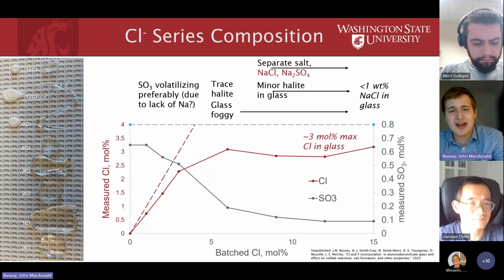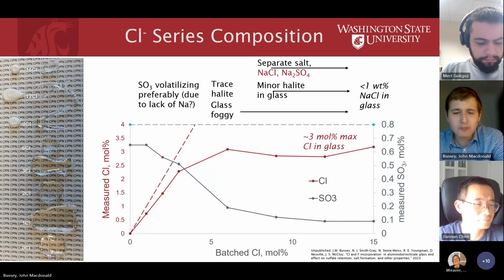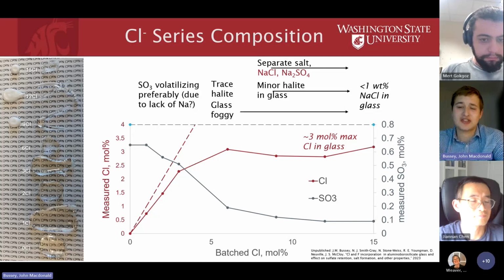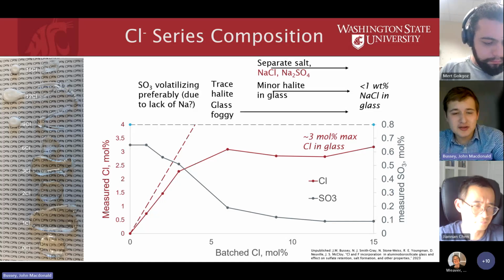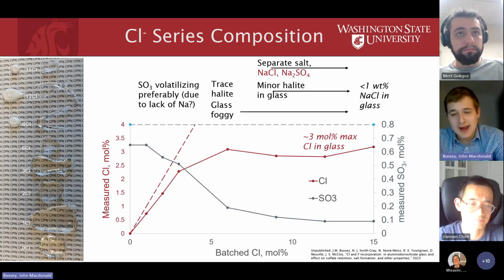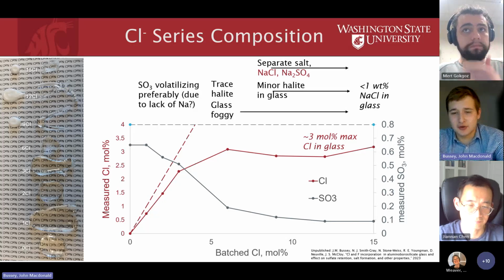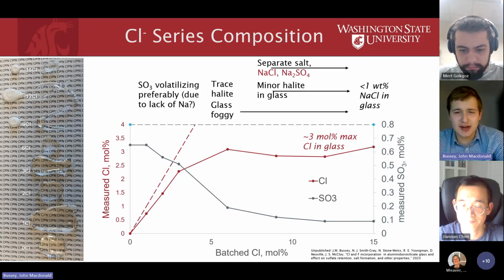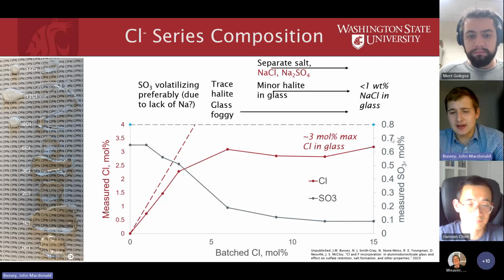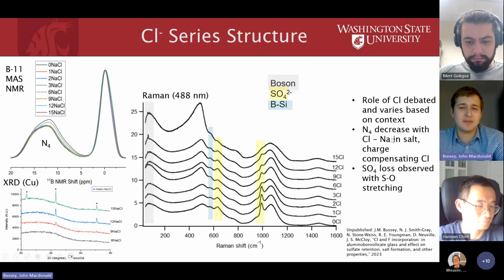And around the same time, we observed that pretty much all of the sulfate crashed out. So the chlorine got up to about 3 mole percent loading, very poor, and it drove away the sulfate. So it indicated to us that the sulfur and the chlorine were probably competing for the same components in the glass.